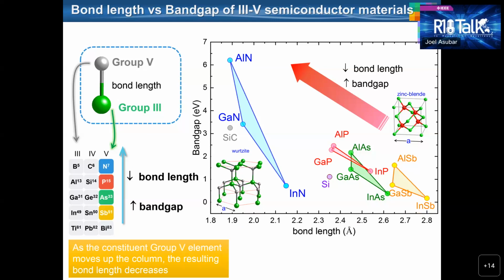Smaller bond length between the group 5 and group 3 element means that the bonding energy between the constituent atoms is stronger. And stronger bonding energy means wider band gap energy, which means that among the III-V semiconductor materials shown here, the nitrides have the widest band gap. And what is the consequence of having a wide band gap? Why is it very important to have a wide band gap?